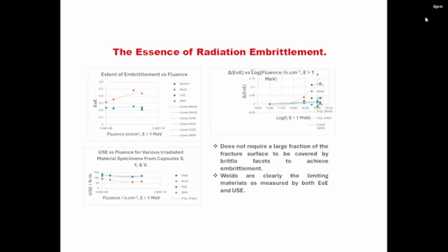And if you look at the upper right plot, you can see that a 10% change in the extent of embrittlement essentially covers the whole range of fluences up to the end of life. And so we're talking about relatively small amounts of change in the fracture surface in order to account for the embrittlement. Next slide, please.